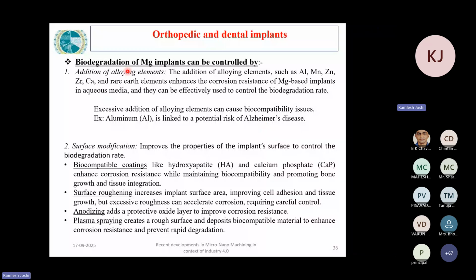Another way to improve the biodegradation is by surface modification. So we can improve the properties of the implant surface to control the biodegradation or corrosion rate. One of the ways is to coat them with biocompatible material like hydroxyapatite and calcium phosphate coatings, which enhance the corrosion resistance and promote bone growth and tissue integration. This is one of the highly used techniques on magnesium materials.